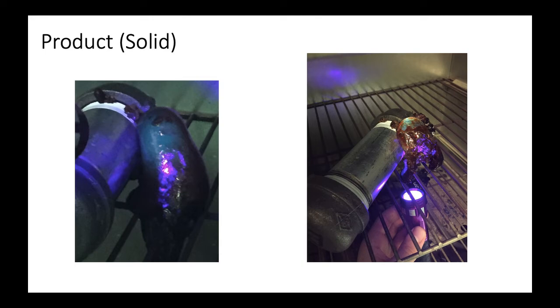Screw-on reactors are notorious for leaking, which you can see by the gelatin bubble that burst out from one of the ends. Even though the seal burst, quantum dots were still formed. Shining a UV flashlight caused the solid phase carbon quantum dots to glow blue, which you can see on the left and the right. The blackened crust is from burnt gelatin, but there are pockets of intact quantum dots still near some of the surfaces and around the bubble.